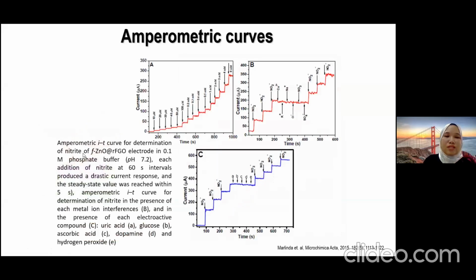Okay. And then to study the kinetics of the material, we also can use the amperometric, which is a current versus time curve, where we can determine the step of the introduction of 10 micromolar of sodium nitrite, and then also we can study the interference by introducing metal ions and also the electroactive compounds such as uric acid, glucose, ascorbic acid, dopamine, and hydrogen peroxide. So you can see that there are no obvious changes observed, even though we introduce the interference.